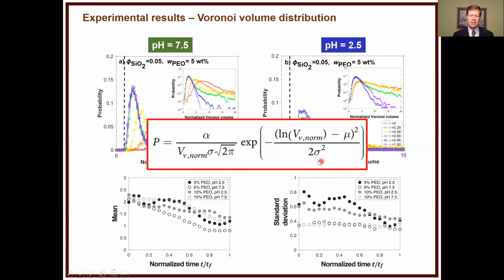In this case, for the mean, what you can see is that the open symbols are those with pH 7.5, and the closed symbols are those at 2.5. The open symbols are always monotonically decreasing in the experiment. And the closed symbols, where it's a gel, sometimes go up and down and fluctuate quite a bit. But what's really telling is the standard deviation.